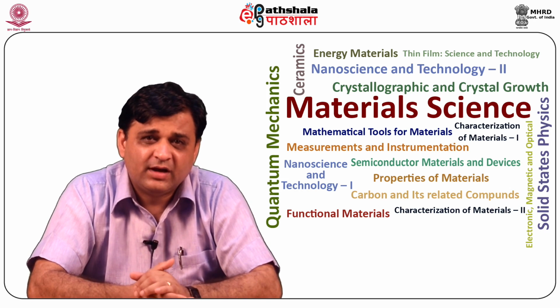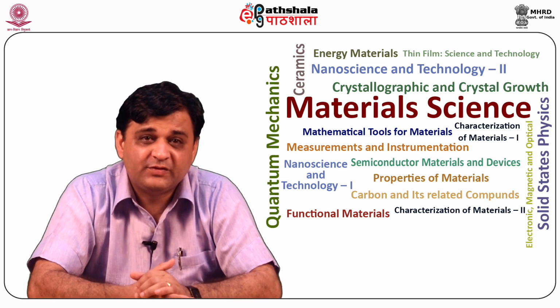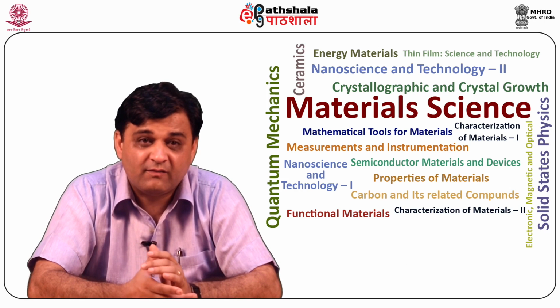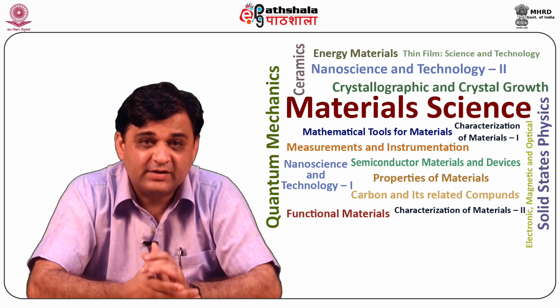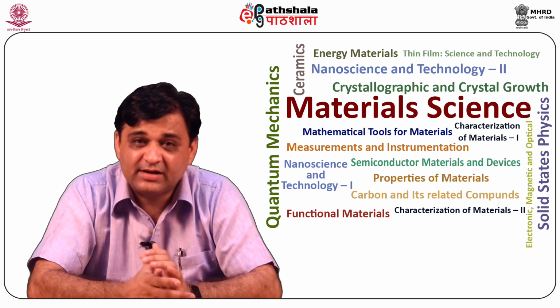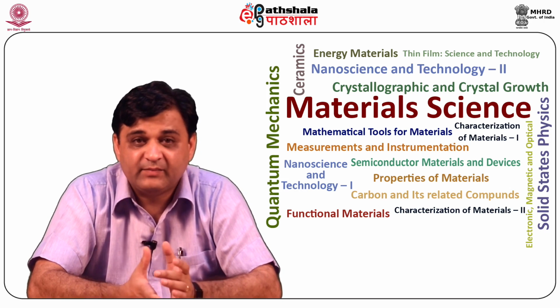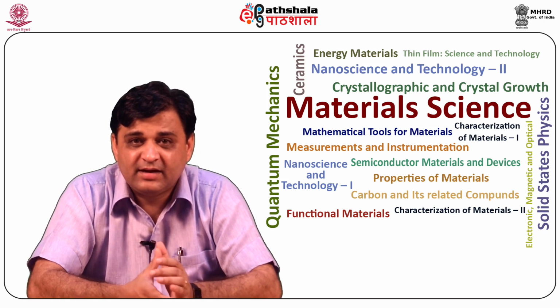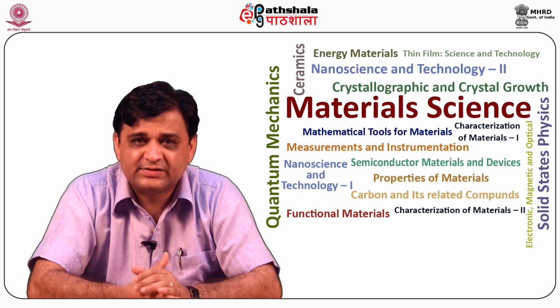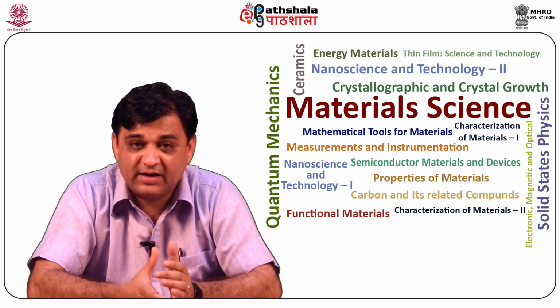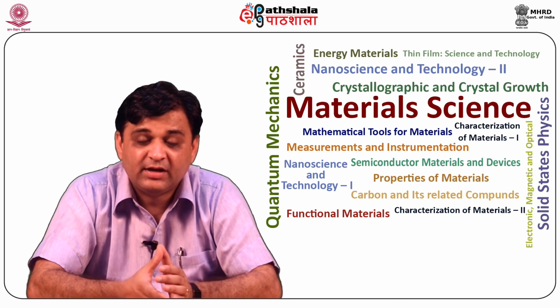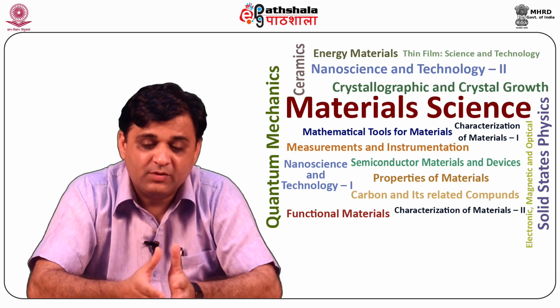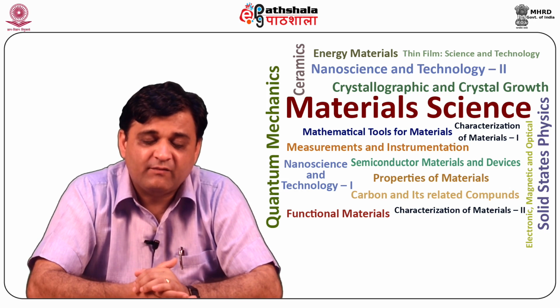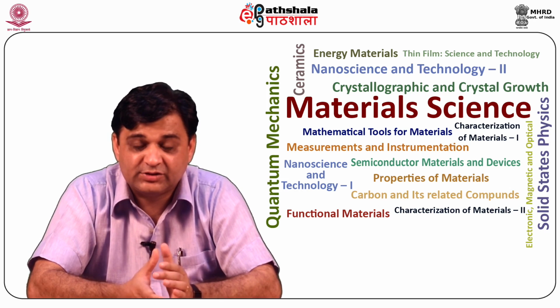In thin films, we have crucial information on the crystalline order and the roughness of buried interfaces that can't be probed with AFM and STM. In that case, grazing incidence techniques such as grazing incidence X-ray scattering, GID, X-ray reflectivity, and neutron reflectivity, which can indeed probe the buried layers inside, become very helpful in the analysis of thin films and the structure of interfaces.